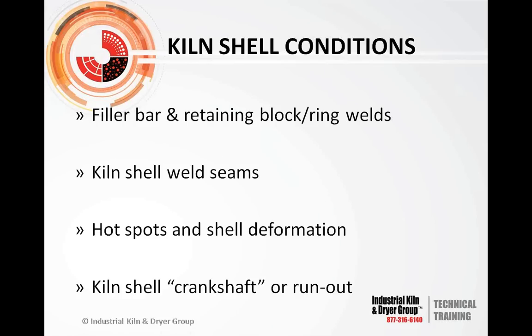Okay, other conditions that you want to look at for inspections: look at the support pads, the retaining blocks, stop blocks. These are areas of maintenance headaches where you get a lot of cracking, wear, different things like that. Keep an eye on that. Keep an eye on all your weld seams on the shells, especially on kilns. Look for hot spots if you've got a hot kiln, shell deformation, and anything that would indicate that you created a crank or a wobble in the shell as a result of losing refractory.